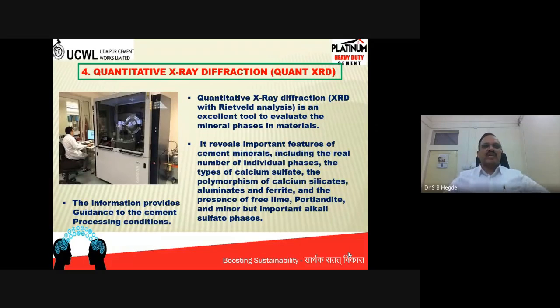For example, we are targeting generally around 50% tricalcium silicate in the cement plant, because tricalcium silicate is the phase which gives strength in the cement. So higher the C3S content, higher the initial strength and the later strength. I am talking about the general compositions. By doing this Rietveld analysis using X-ray diffraction, you will come to know how much is really there. How much real tricalcium silicate is there in the clinker or in the cement?